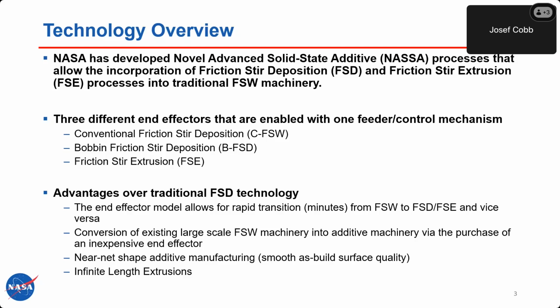We get near net shape and net shape parts when we're done. So we get a smooth as built surface. So we don't have the surface quality issues you'd have with meld where you need to machine a 1/4 inch off, and that picture on the front, it just won't die, right? So we've got some much better depositions than that. And then for the extrusion side of things, infinite length extrusions.